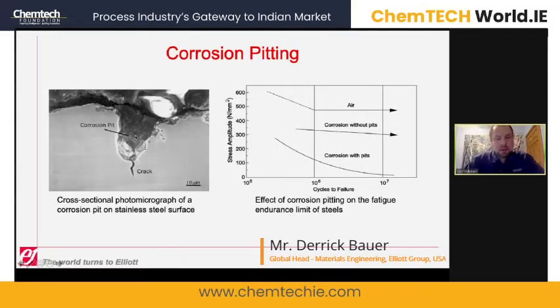Shown on the left is a photomicrograph. It's a cross-section of a corrosion pit, where what you see on the surface is a little round dot, but underneath of that and going into the material is a very sharp crack. It is especially chloride corrosion pitting, where it goes along grain boundaries of the material and makes a very sharp, atomically sharp crack, really, and this creates a very high localized stress intensity.